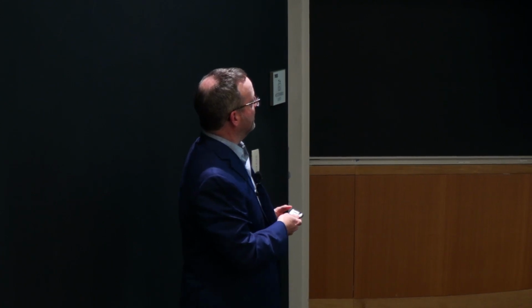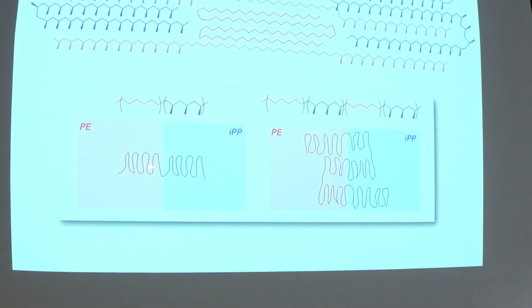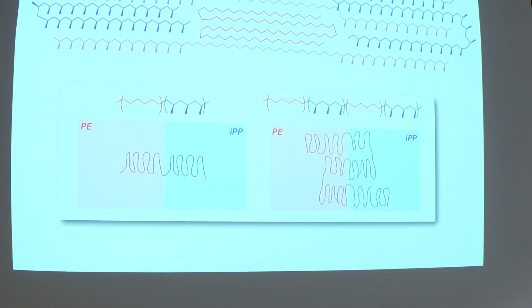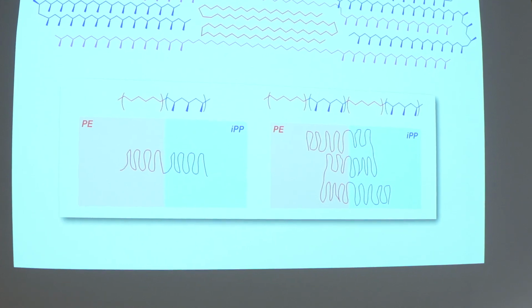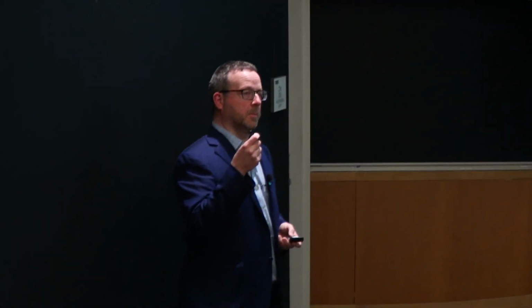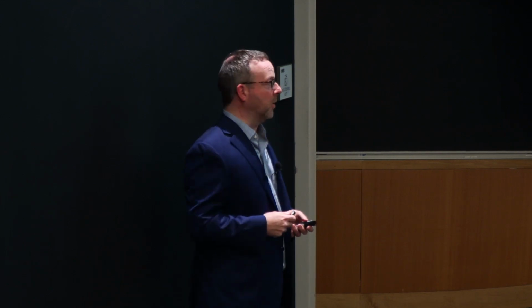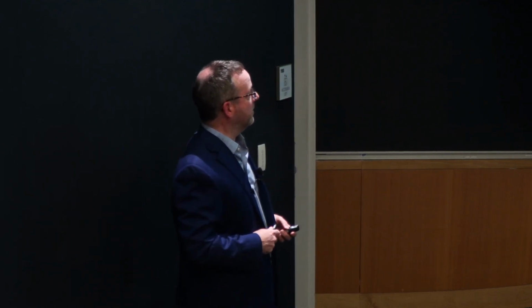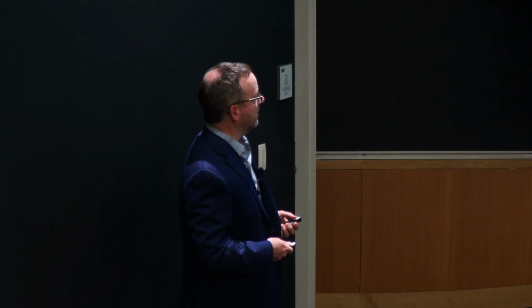And so we decided to look at some of these molecules, a little better idea of what, if you make a diblock polymer, you would have your polypropylene phase and your polyethylene phase. And a diblock would be a stitch. And maybe a stitch is strong, but many stitches would be better. And if you start to make things like tetrablock polymers, that could then weave back and forth over the interface. Not to mention, it can also then entangle into the polyethylene and polypropylene chains, not only just co-crystallizing, but actually commingling in a mechanical way with both polymers. And so we decided to test this idea. A number of people looked at diblocks, and they don't work very well, but we were hoping that maybe by looking at some new architectures, we might be able to impact performance.